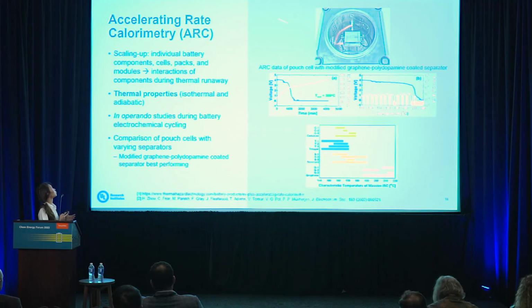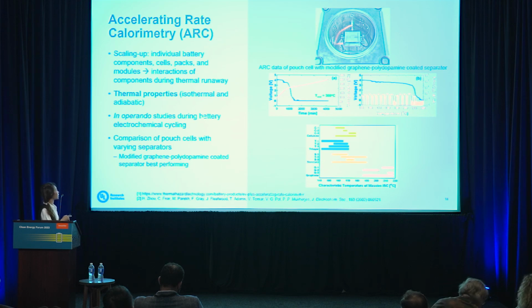Another thing that we can do is the accelerating rate calorimetry, the ARC testing method. It's not just for individual battery components, but we can also test cells, packs, and modules. It's a really good tool. As you can see here, this is a chamber, and we can understand the interactions of the different components during thermal runaway. It can be run in the isothermal or the adiabatic modes. It's also an in-operando study, so you can actually track the voltage of the cell as you're performing the ARC testing.